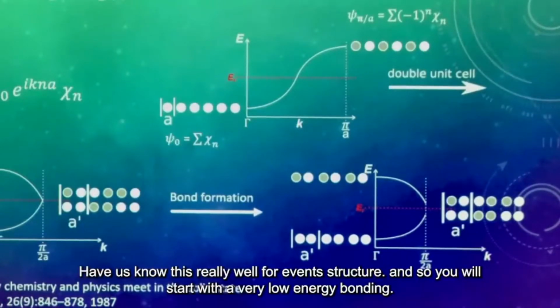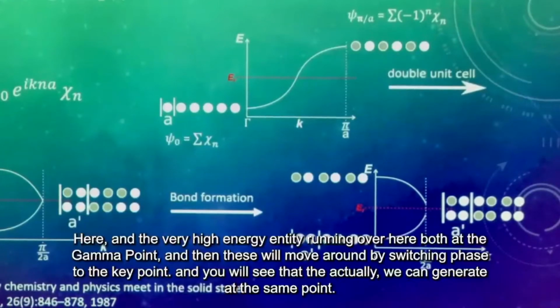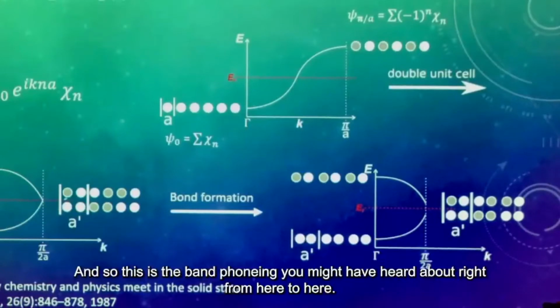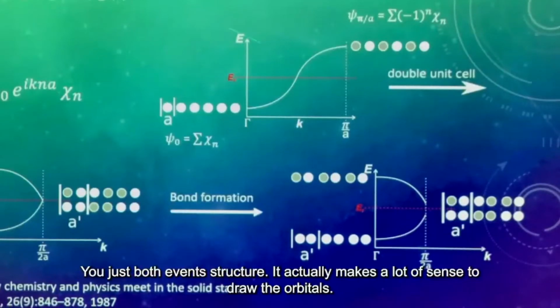And so you will start with a very low energy bonding orbital here and a very high energy anti-bonding orbital here, both at the gamma point. And then these will move around by switching phase to the K point, and you will see that they actually become degenerate here at the K point. And so this is the band folding you might have heard about, right? From here to here, you just fold the band structure, but it actually makes a lot of sense if you draw out the orbitals that this is happening.